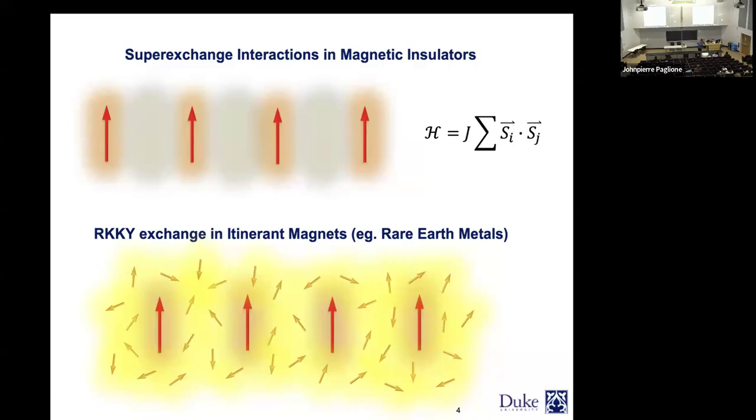In the case of an exchange interaction, you can basically write the Hamiltonian, depending on what kind of interaction it has. That interaction comes from the fact that you're going to have some sort of a bond between these magnetic ions, right? You can have oxygen, you can have chlorine, and that angle is also going to be very important. So the way those orbitals make an angle with each other and who's the ligand between them is going to tell us whether you have a ferromagnet or an antiferromagnet, and how strong those interactions are going to be. Okay?